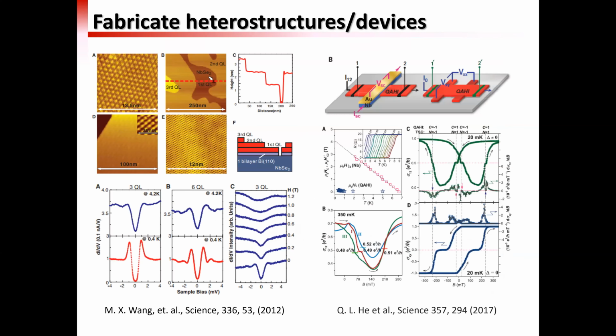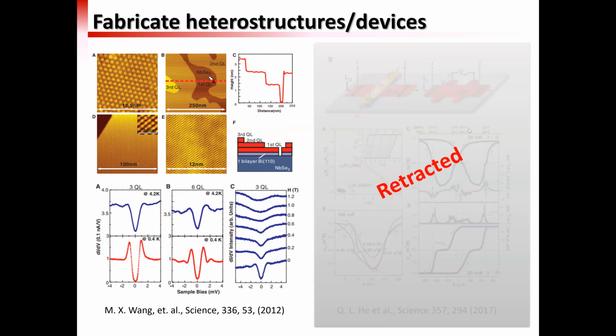For example, you just grow a layer of topological insulator on a conventional superconductor, like bismuth selenide on niobium selenide. And people also fabricated more sophisticated devices, trying to realize and observe the characteristic signal from the Majorana fermion. But unfortunately, this route turned out to be quite difficult. For example, one of these works was recently retracted, and this was on 2D films.